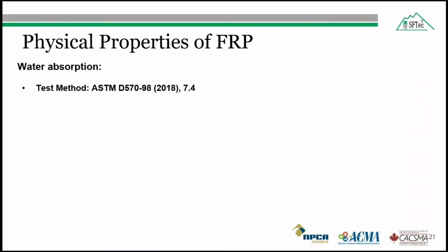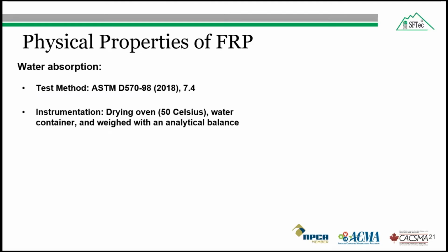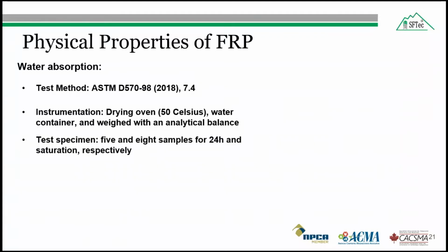So the next test is the water absorption, and the FRP specimens were tested in accordance with the water absorption procedure 7.4 in the ASTM D570, which was re-approved in 2018. And the instruments used in the test were drying oven capable of maintaining the required 50 degrees Celsius. A water container was used for absorption. The specimen were weighed with an analytical balance to 1 milligram precision.